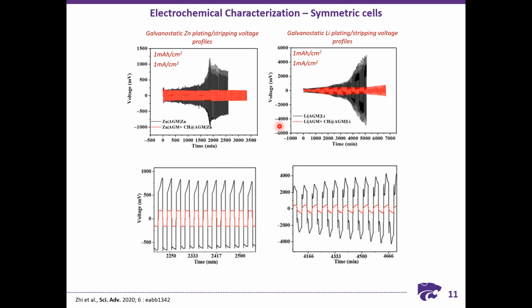So then they made some symmetric cells, both zinc as well as lithium, to see how it works. So as you can see from here, they were cycled at a rate of 1 milliamp per centimeter square for a capacity of 1 milliamp hour per centimeter square. And as you can see here, the black lines are the case of zinc without the use of an interlayer. With the increase in number of cycles, the overpotential for metal plating and stripping continuously increases, and after certain time, because of the growth of SEI and the increase in resistivity, it increases quite dramatically. While in the case of use of a CB@AGM interlayer, it is quite stable. Both the plating and stripping overpotentials are quite stable for more than 3000 minutes.